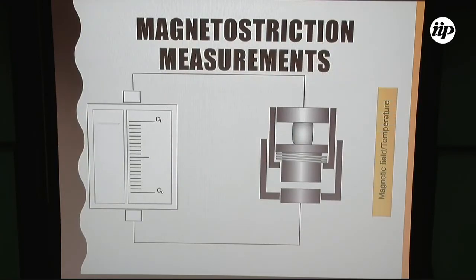Magnetostriction measurements are very easy to perform. Use a capacitive cell. When a field is applied, the sample changes size, and the distance between the plates of the capacitor changes, which is associated with the expansion of this material.